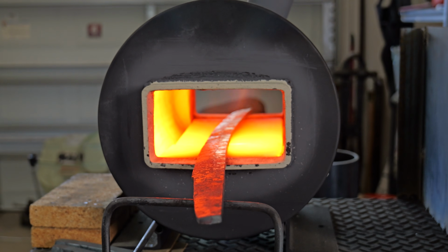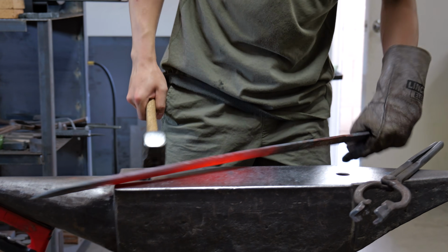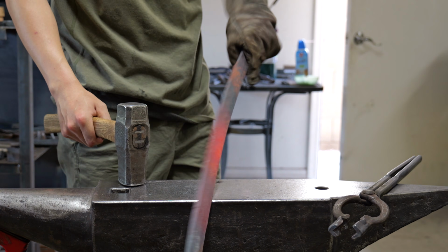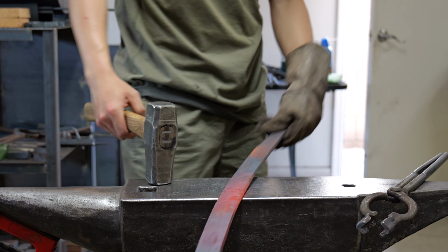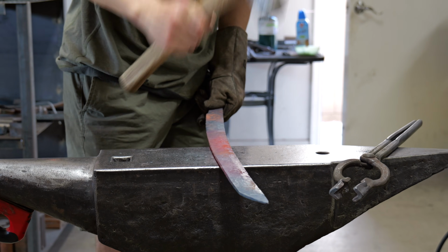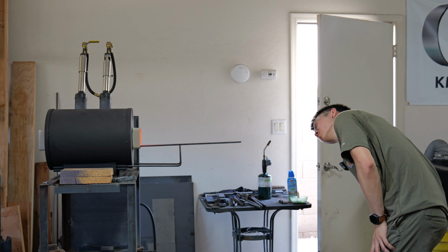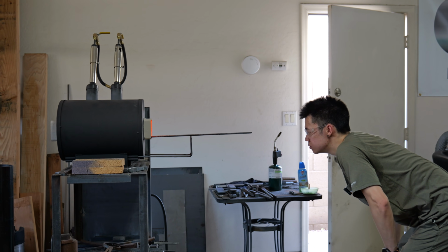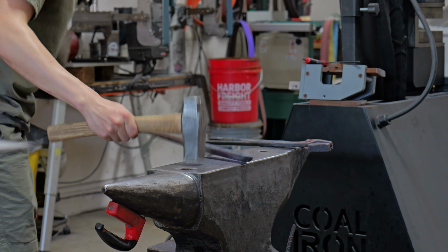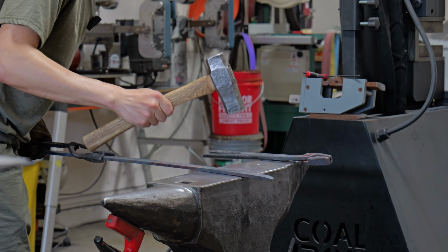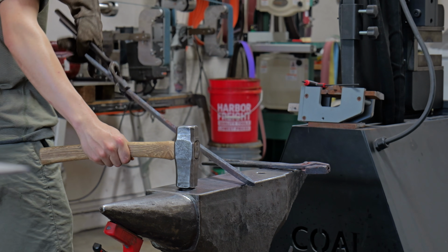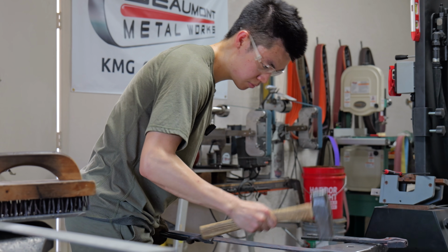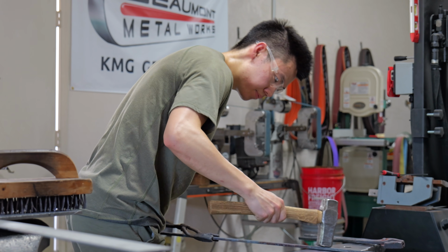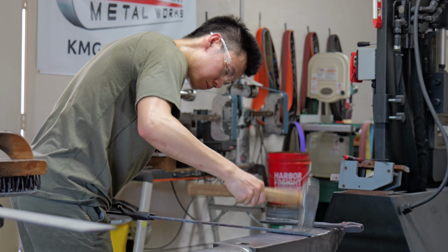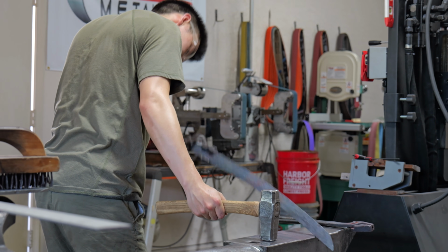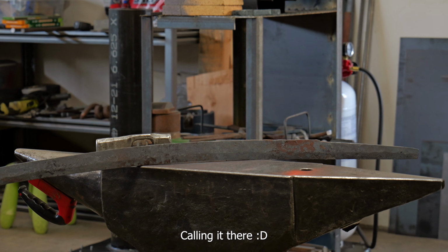If you know a lot about katana, you're probably wondering how come my blade already has a curve in it. Aren't you supposed to get that curve when you quench it? And the answer is both yes and no. If you were to quench it in water, you would get more curve, but I'm quenching it in oil. And when you quench in oil, it actually bends the other way. So I actually have to bend it more than the final bend. And eyeing that out and making sure that the blade is straight is actually a lot of work. I also have to make sure that the edge is centered to the straight blade. And that itself is another can of worms. Calling it there.